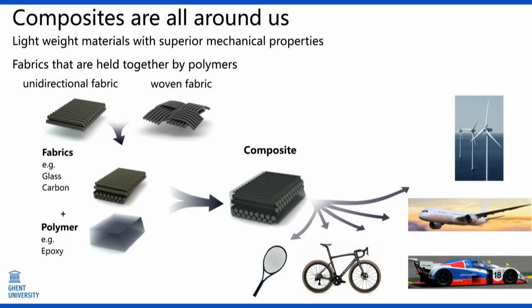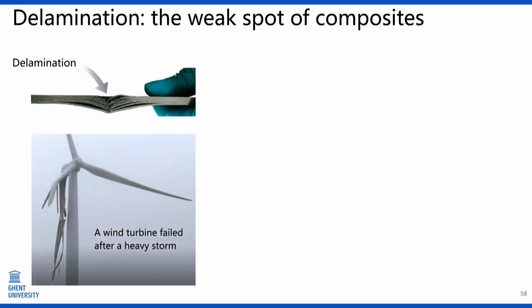And then when I'm talking about composite materials, I'm talking about fiber-reinforced composites. And these are the type of materials we all know. They're all around us, and they're used because of their light weight and very high mechanical strength. And they're typically built up of textile fabrics, unidirectional or woven fabrics, stacked on top of each other and embedded in a matrix. The fibers are typically glass or carbon fibers, and the matrix is typically an epoxy. So they're very high-end materials, but they've got an important weak spot, and that is delamination. Because of the brittle nature of the epoxy, they're very sensitive to delamination, and once they delaminate, they give an immediate failure, which is to be avoided.